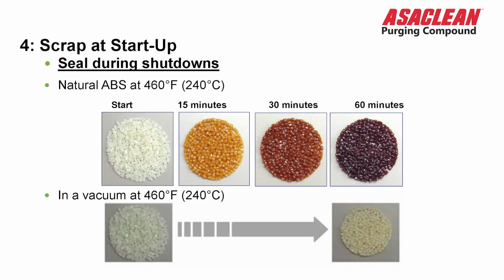Again, this is an adaptation of how quick an ABS can degrade on a shutdown. Obviously, if you take a look at the start, it's nice and pristine. Just after 15 minutes, that ABS at 460 degrees is going to begin to degrade. After 30 and 60 minutes, you see what the outcome is. And that's just due to time and temperature.